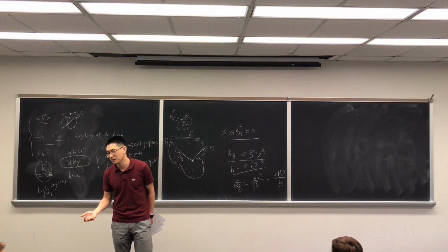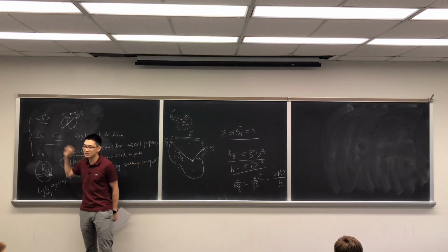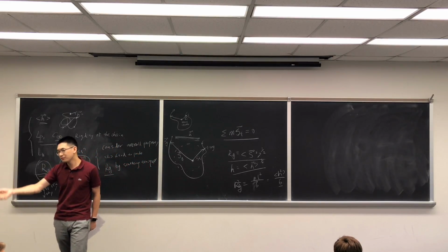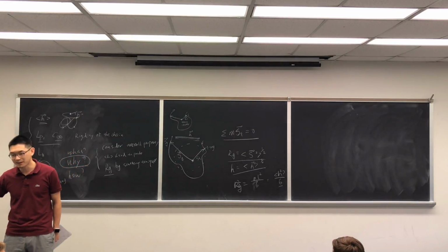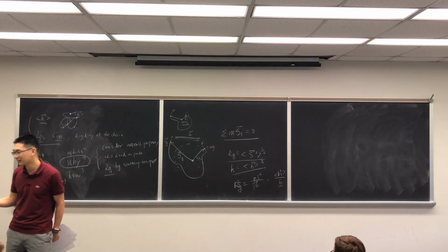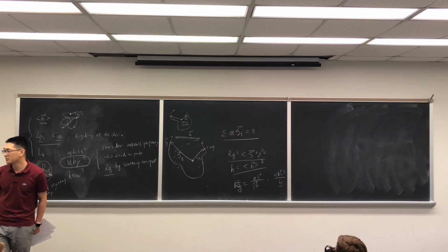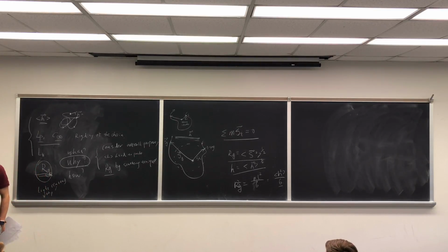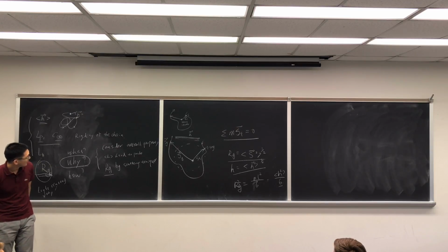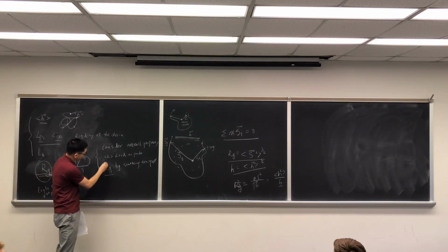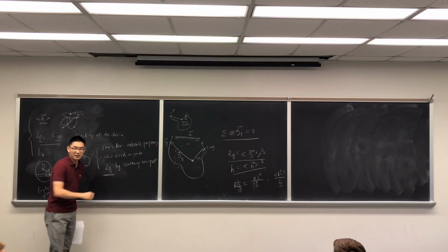You just multiply by √6. What you're going to get is the end-to-end distance. And if you know the degree of polymerization, then all the rest is easy. You can calculate characteristic ratio, chain rigidity, etc. So that's the whole reason why we actually measure Rg.